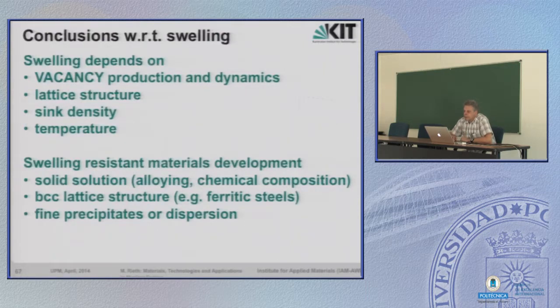Concluded, swelling depends on vacancy production and vacancy dynamics. It depends also on the lattice structure. You can influence it by the sink density, the number of precipitates or dislocations. And it also strongly depends on temperature, since there is only one peak in temperature with regard to swelling.